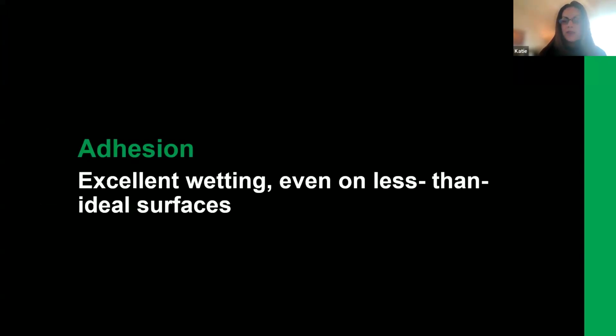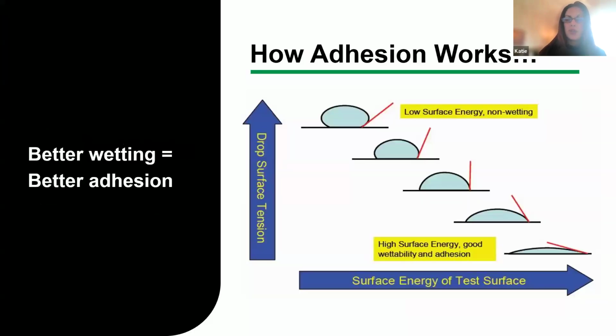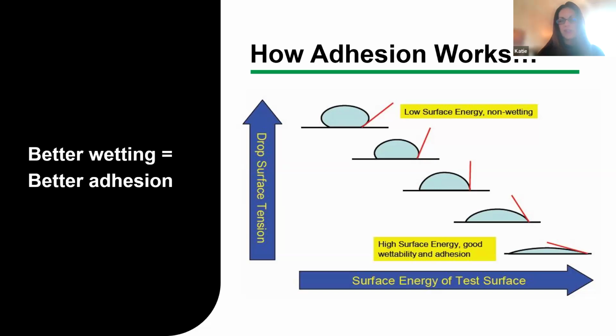This is determined by the wetting characteristics, and surface tolerant coatings need excellent wetting, even to less than ideal surfaces. And this is how adhesion works in a visual. The goal is high surface energy and low surface tension. You can see at the top that the low surface energy has a tendency to create droplets, and those bead up, which can create voids in the coverage to the substrate, where high surface energy allows for better coverage and better wetting. And when you have better wetting, you have better adhesion.